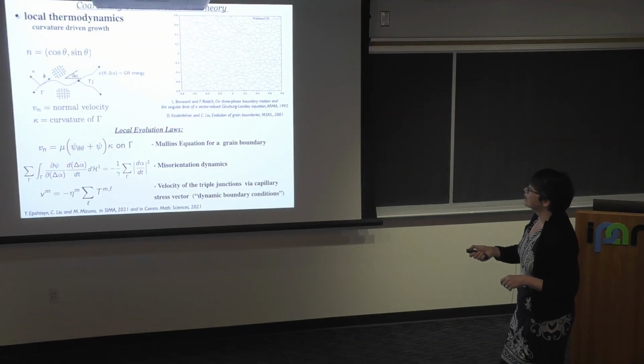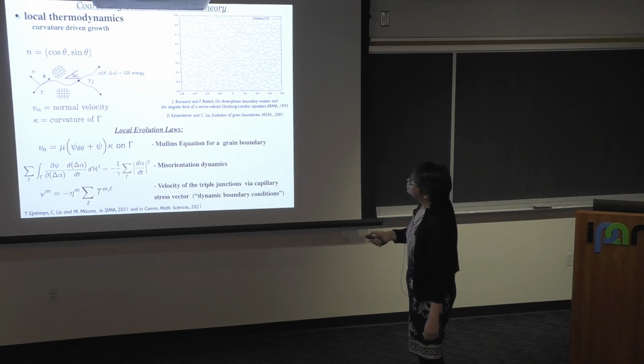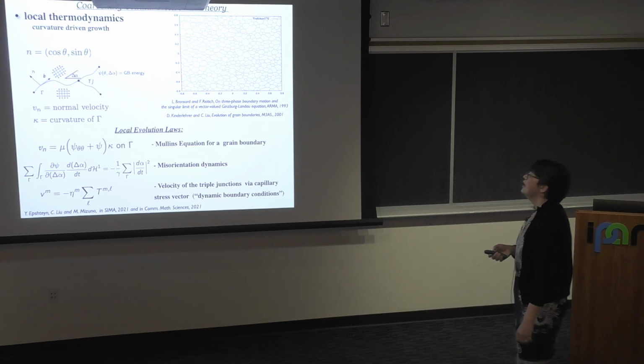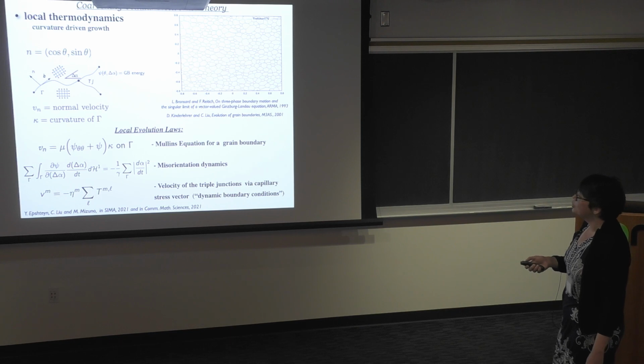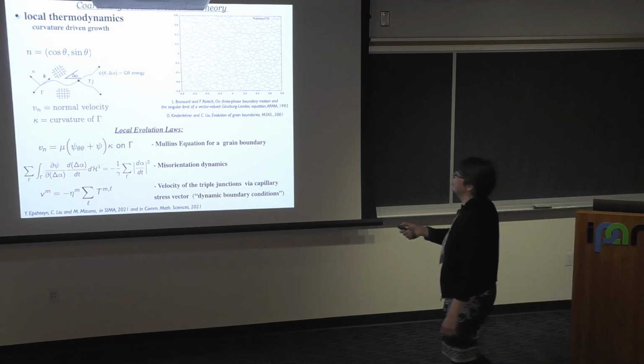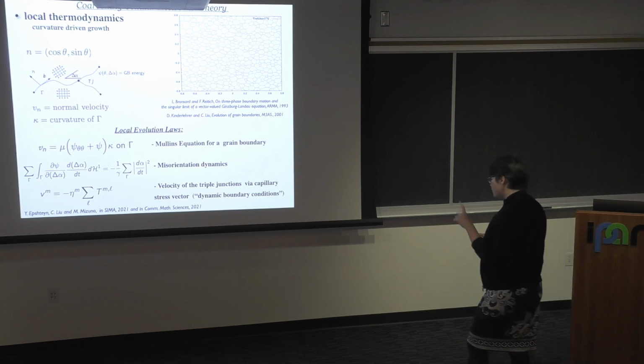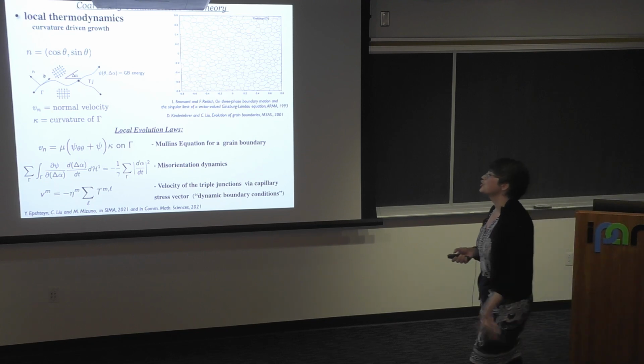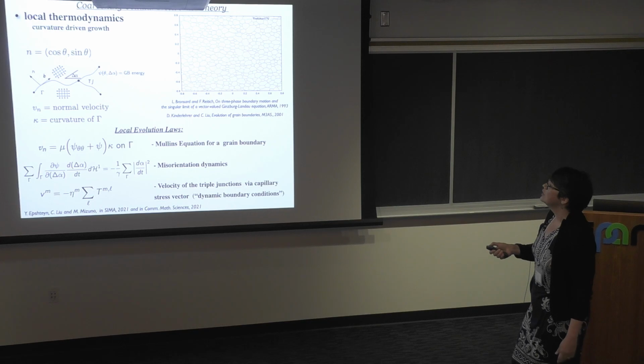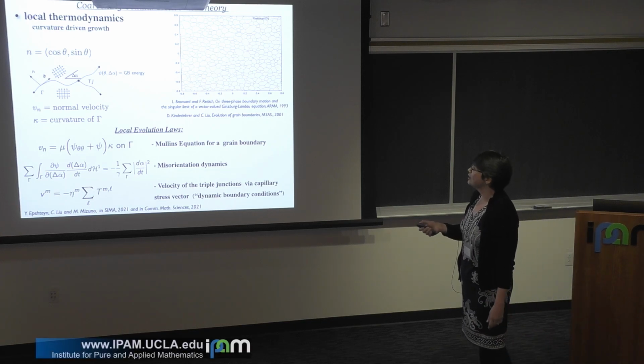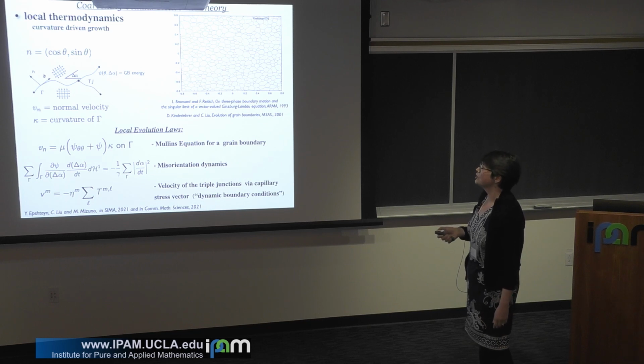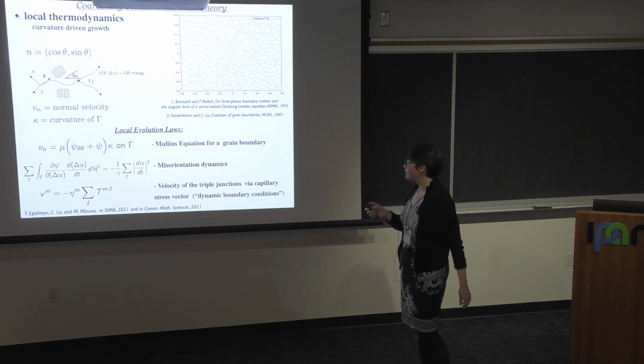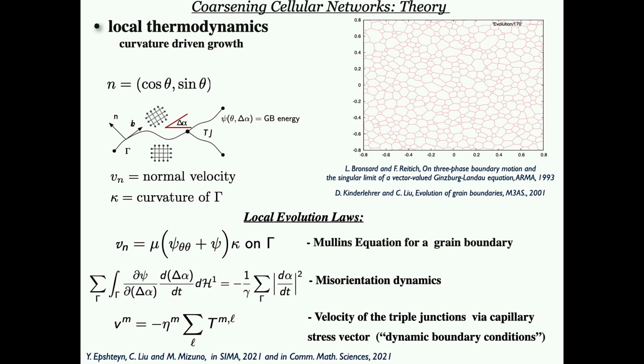So here, each curve represents a grain boundary, which is defined by a normal vector and tangent vector. We also assume that each grain boundary carries excess of grain boundary energy density denoted by psi. So in our model, we assume that grain boundary energy density only depends on geometric features of grain boundaries, namely the normal angle and misorientation angle, which is the difference between orientations of two neighboring grains. And later, I will even simplify further. I will assume that we have only dependence on misorientation angle, delta alpha, in order to isolate certain effects.